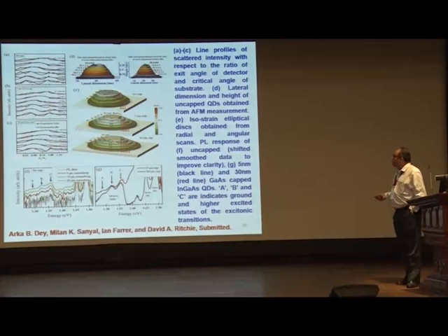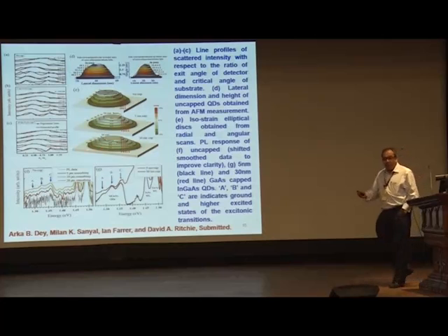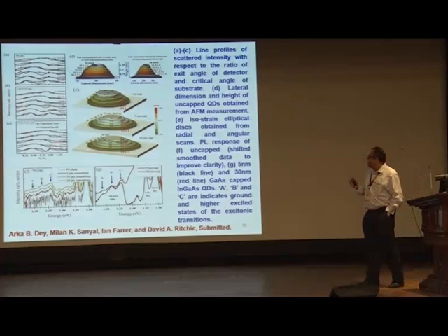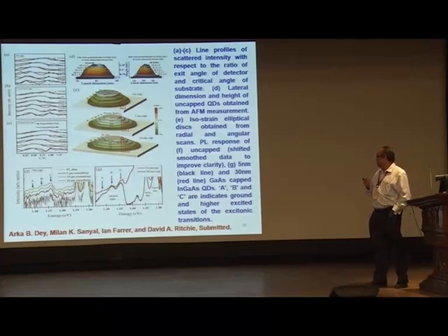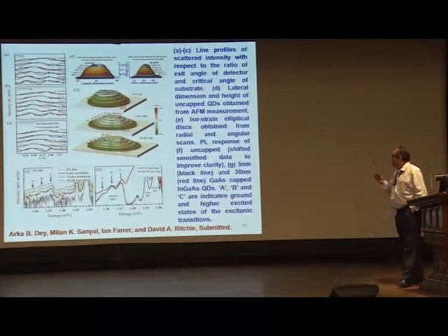I will say these are average quantum dots, because many of them are illuminated by X-ray. Now, we are trying to see whether we can reduce the number of X-ray illuminated dots because of the availability in Petra 3, DESY, of a very intense X-ray beam, and we can grow the sample in such a way that we can reduce the number of quantum dots which are getting illuminated by the X-ray beam slowly. So, right now it is about 10,000 quantum dots which are getting illuminated. So, we come to 1000 and then 100 and then finally 1 maybe. So, we will get composition